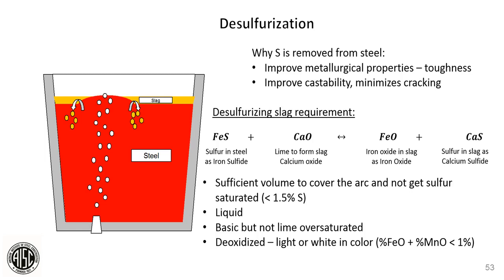So you've got iron sulfide in the steel, and liquid lime in the slag, and you've got FeO and calcium sulfide in the slag. Basically what we're trying to do is work everything to the right, where we make calcium sulfide in the slag, and the FeO we'll take out with the calcium carbide. But you've got to have enough slag to make sure it's not supersaturated, because eventually the slag is a sponge, and if it gets too full of sulfur, it'll stop working. It can't take any more. So you've got to have enough lime in there to make enough slag to remove the sulfur. It's got to be liquid, can't be solid. It's got to be basic, but not too much calcium oxide, and it has to be deoxidized with calcium carbide. Next slide, please.